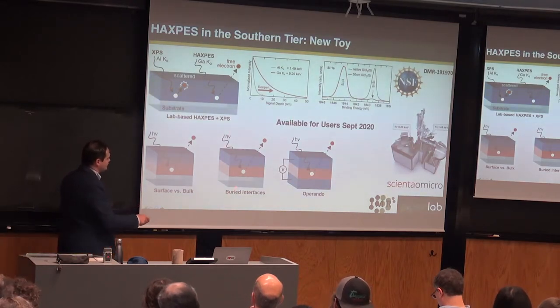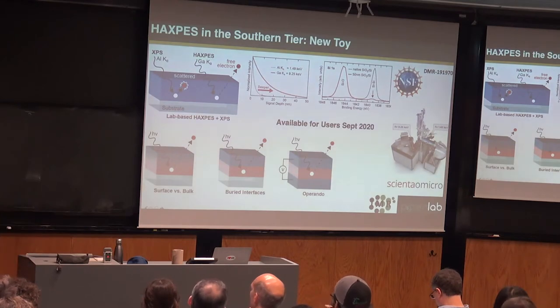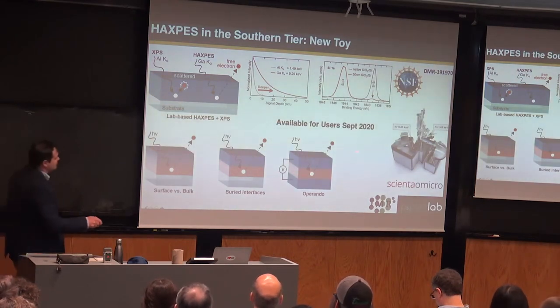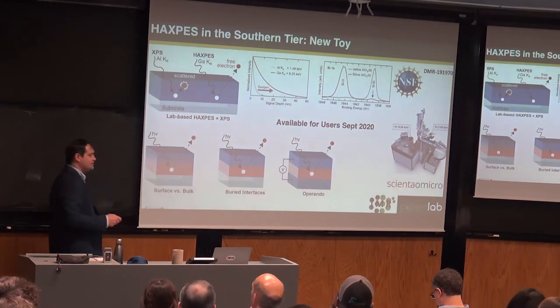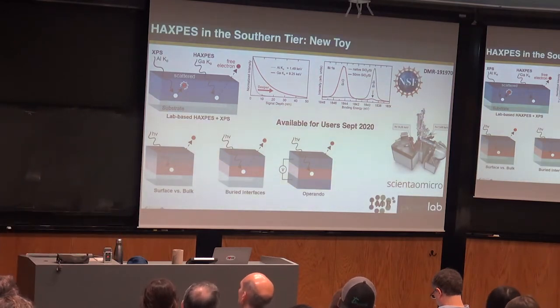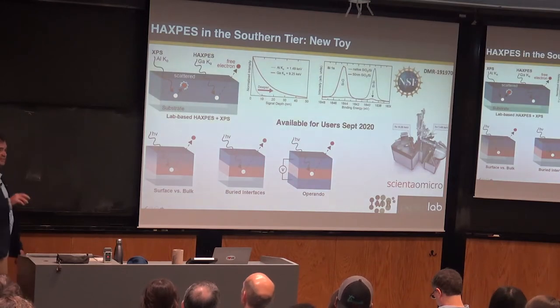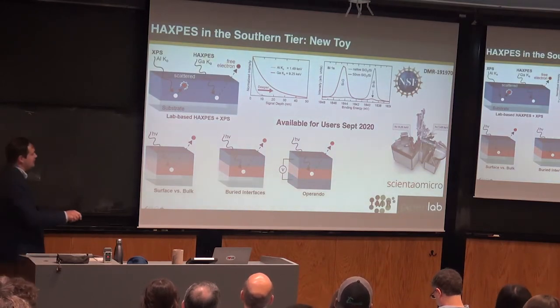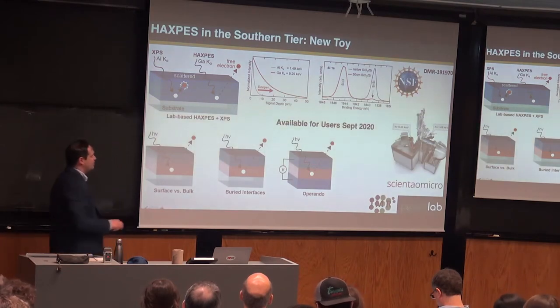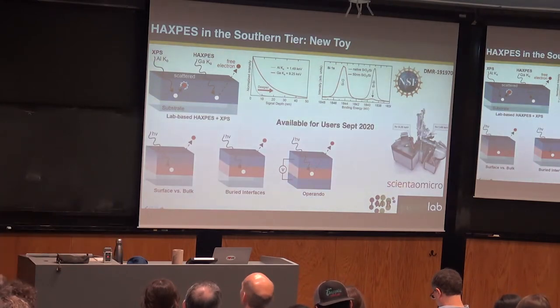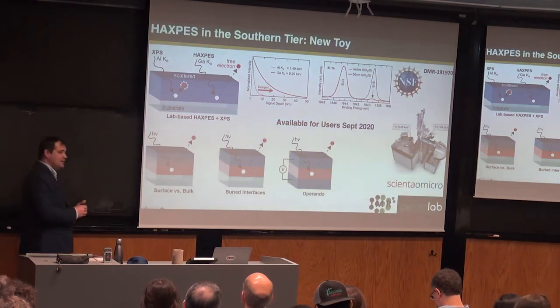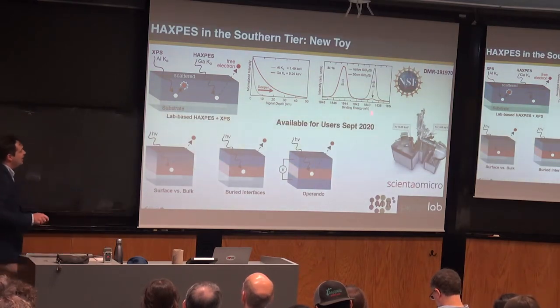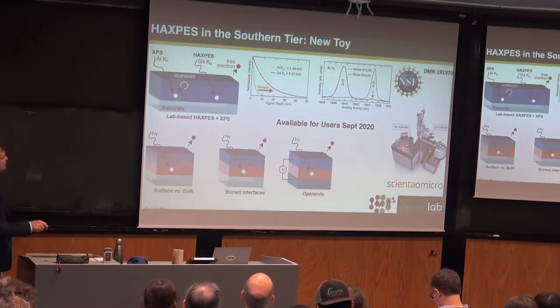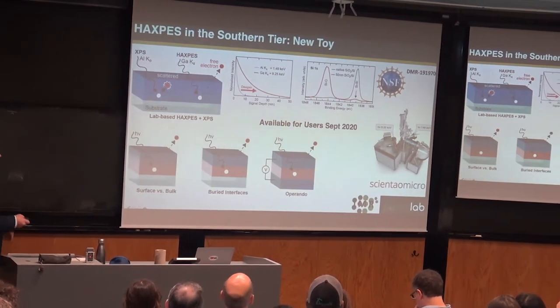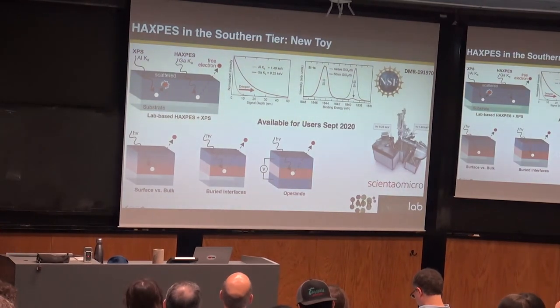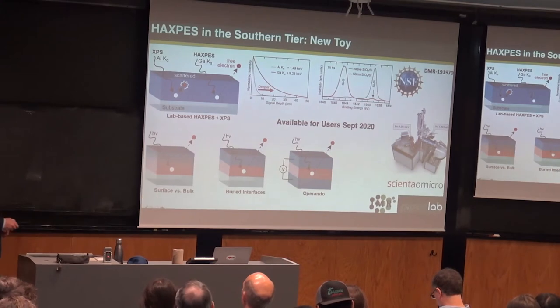We can study non-destructive buried interfaces and determine band alignments. That's important for this project. But going forward, because we don't disrupt that interface, and to quote another Nobel Prize winner, Herbert Kroemer, the interface is the device. So you don't want to compromise that, and because we don't need to, we can also run this with bias. So this system will be available for users, and it's only a short drive down the road. Be careful of deer. And this system will have a two-color system because it'll have both the soft and hard X-rays. It will also have an inert vacuum transfer system, so you can put your precious systems in inert conditions all the way through.